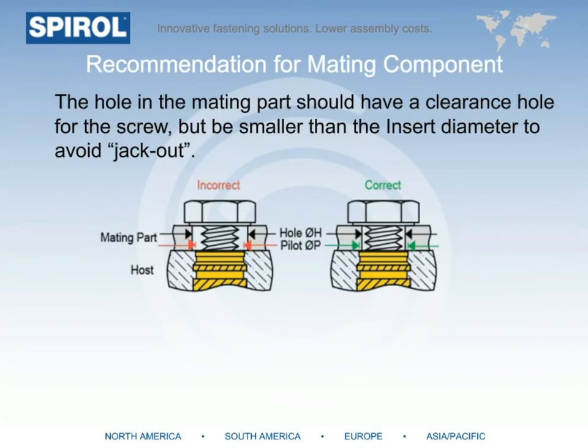And it's not just that interface between the insert and the plastic host component that is critical to performance. The mating part also can significantly reduce performance by not providing enough of a bearing surface on the insert, which we call a jackout condition. With the hole size in the mating component larger than the face of the insert, there's nothing we can do to prevent the insert from dislodging and moving up into the void of the mating part. To avoid jackout, we recommend that the mating component's hole is smaller than the face of the insert, but large enough so that the bolt can pass through.